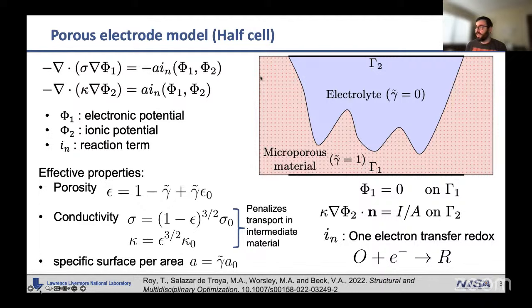So you define it piecewise with an interpolation using your design variable. And then in terms of penalization, we did porosity to the 3 halves like this. This is actually just the Bruggeman correlation, which is used in diffusion through porous media. And it turns out this is a very decent penalization. So we don't even need to change the physical equations, and it works as a decent penalization. You'll see in the next talk, we changed that a little bit.